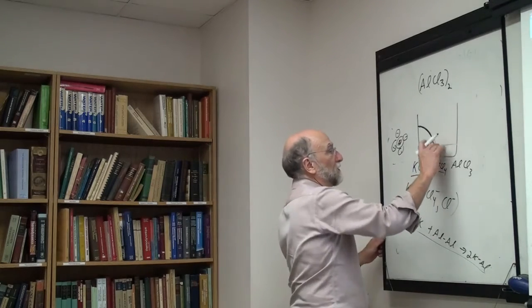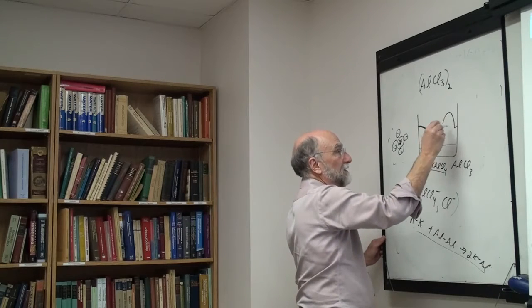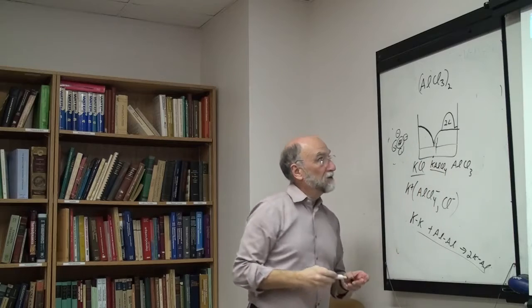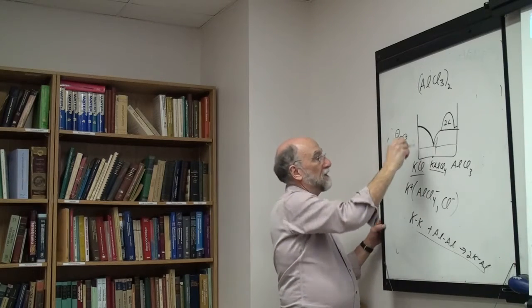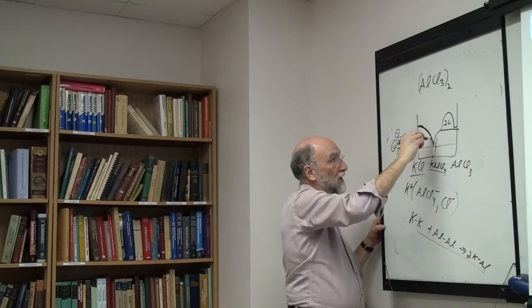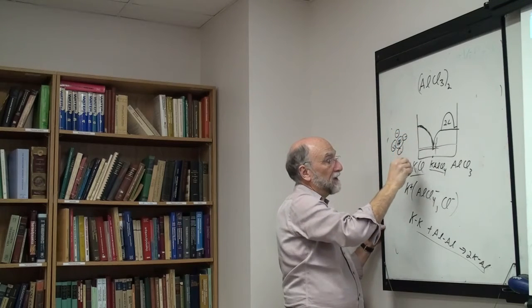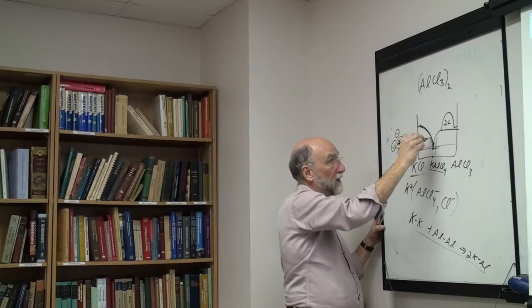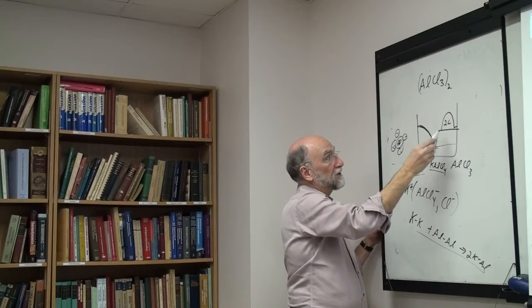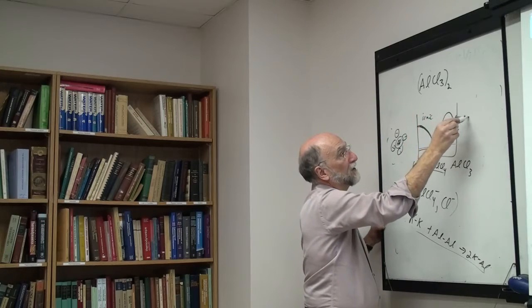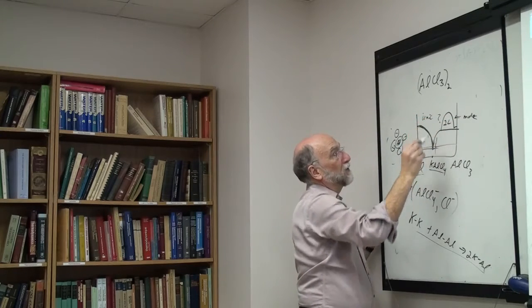What this gives you, the phase diagram, looks like this, with two liquids here. There are some compounds in here, but this is basically how it works. The liquidus goes down very, very steeply. This is a very low valley because you've lowered the activity of the KCl very greatly by complexing. Over here it's ionic, over here it's molecular, and in here it's whatever.